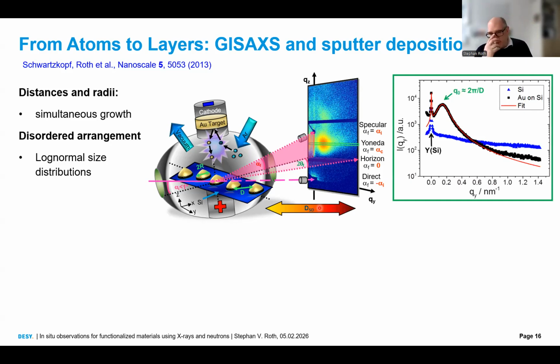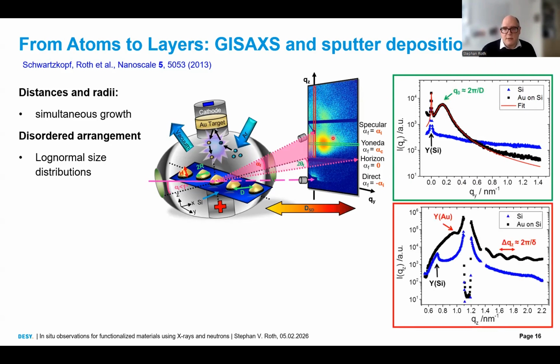And here we have developed an analysis method. When you see a side peak, we can relate the side peak again to the position. This is like a Bragg peak. Peak means 2 pi over d, and d is the distance. When we look in vertical direction, we see again here the Yoneda peak, in that case of gold. This is a specular reflected peak. We don't need it, we block it in order not to harm the detector. And then you again see here fringes, which tell us the thickness delta of the deposited, in that case, gold layer.